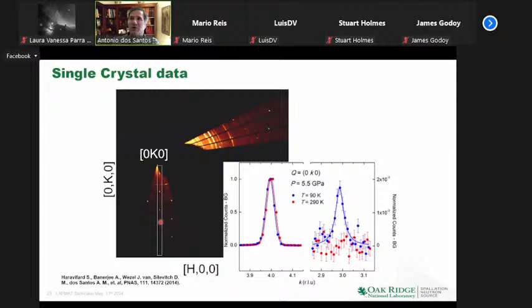The other thing that you get with single crystals is a huge increase in sensitivity. It's not visible in this plot, but if you know where to look, you can see here the scale is 2,000ths of a neighboring nuclear peak, I believe the 040. And we could demonstrate that the 030 appears at high pressure and disappears at room temperature. So this is the magnetic structure. We broke the Shastry-Sutherland frustration, and we're probably in the regime of long range order.